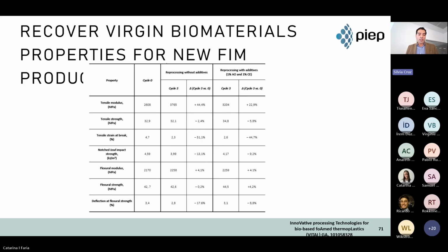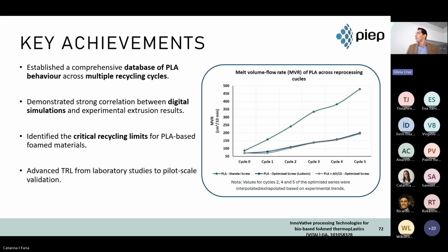So the results were quite interesting, I would say. It was a massive experimental and simulation study. But in the end, I think we can say that we were able to at least establish a comprehensive database of PLA behavior across these multiple recycle cycles. In the graphic that you see the difference between the MVR evolution, I would say, with the conventional screw profile and conventional processing parameters.